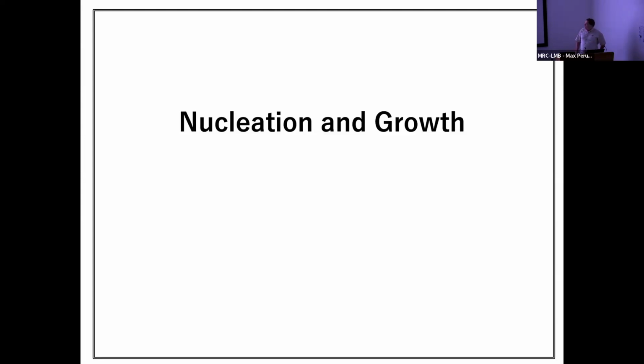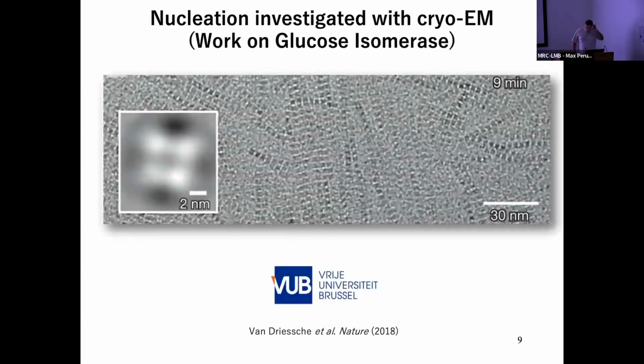Crystallization is usually studied according to two main steps, nucleation and growth. Cryo-EM is increasingly used to better understand nucleation. Observation using time-resolved cryo-transmission electron microscopy suggests that nucleation of glucose isomerase progresses through specific interaction between only a few protein molecules at a very early stage of nucleation. Before that, the theory was more about a global process. There was this kind of aspect where the specificity of interaction was not seen at the beginning.